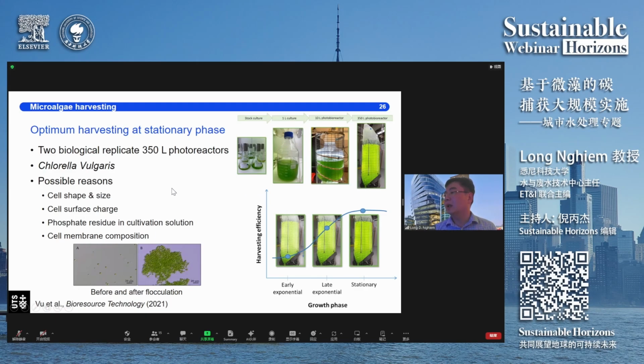Number one, as the microalgae grow, there are some changes in cell morphology, shape, and size, and the surface charge of the microalgae cell will also change. And as microalgae grow, it consumes phosphorus, and therefore the concentration of phosphate in the solution will decrease. There has been some previous work in the literature that shows that phosphorus might impact the flocculation efficiency, and we want to check all of that.